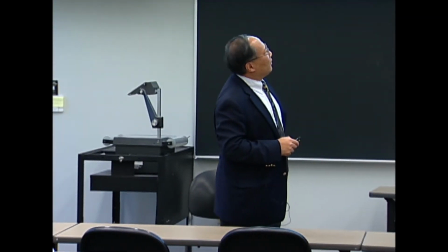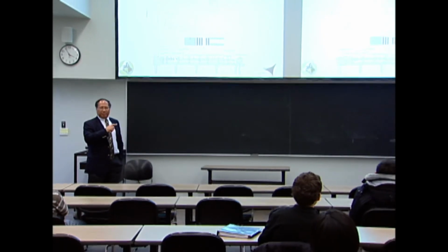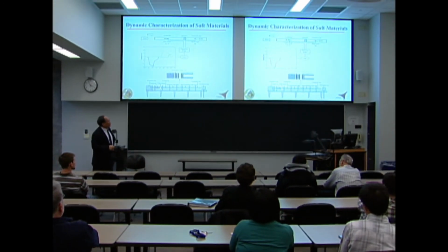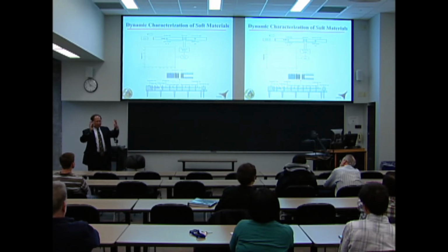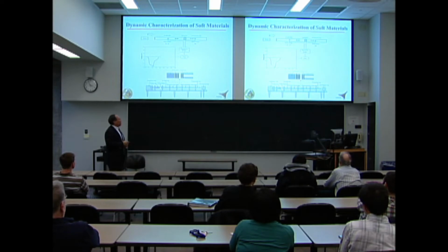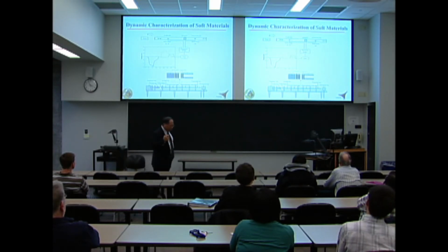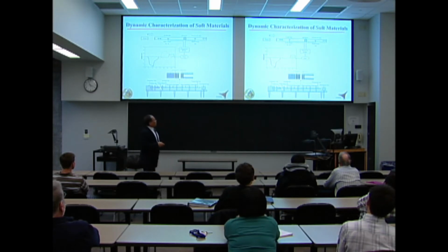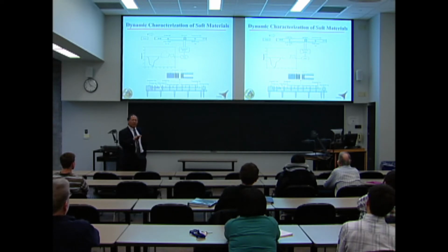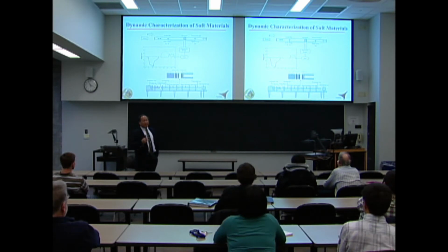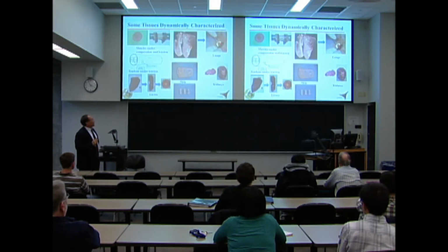Once we have this quantitatively set up, now we can do the experiment. The impact loading history will be very different, but that would take an expert in impact mechanics to understand why this is very good. But we also verify by measuring whether the two sides of the sample have the same loading history. And we also have a high-speed camera to show that the samples indeed deform uniformly. So this is one example. If you have a soft sample, you need to take a series of measures to make sure that you obtain valid results. On the other hand, if a sample is brittle, you have another set of problems, that the sample breaks very early. So you need to develop many other techniques.